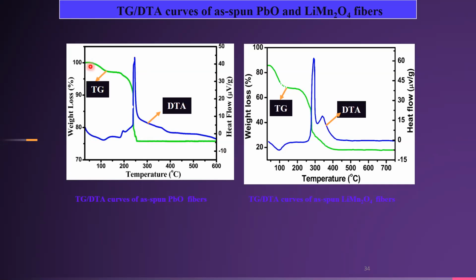The first stage shows a weight loss of 2.60% up to 110 degrees centigrade in the TG curve, which corresponds to the removal of absorbed moisture in the dried polymeric intermediate, with a corresponding broad endothermic peak in the DTA curve.